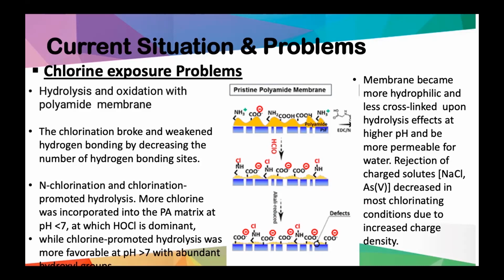So this very sensitive layer can be broken down, its hydrogen bonds weakened, and the nitrogen bonds will be destroyed through hydrolysis by chlorine, which is very favorable when the pH is increased. This means that the membrane will lose its active layer and begin to lose its properties; I want to say, the membrane will lose its activity.